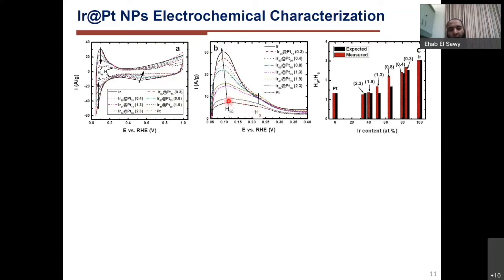By tracking these changes and comparing them with the theoretical value that we calculated for the coverage, we found that they match very well, except at the 1.3 monolayer, which may indicate that we don't have a complete, perfect layer and that it has some defects.